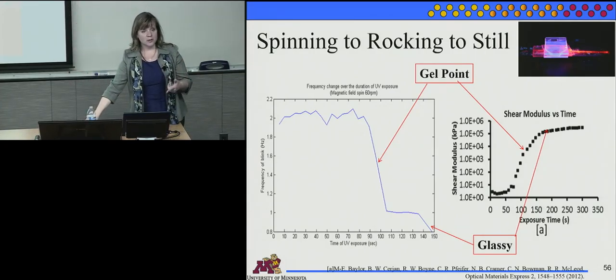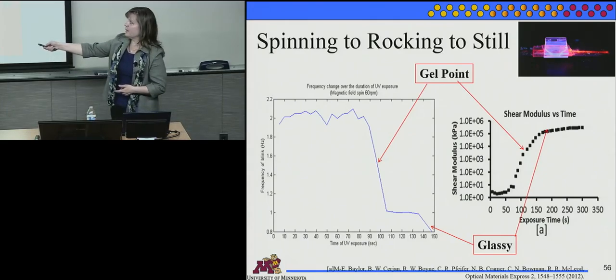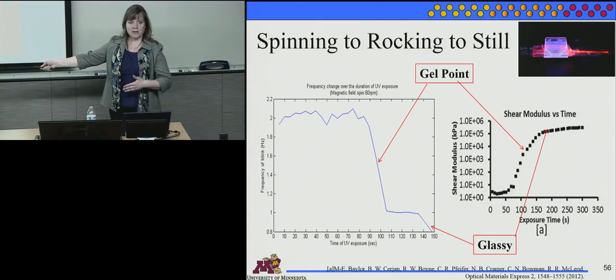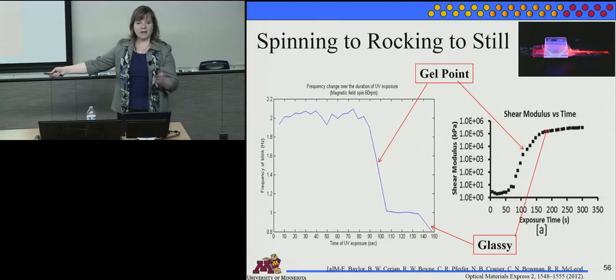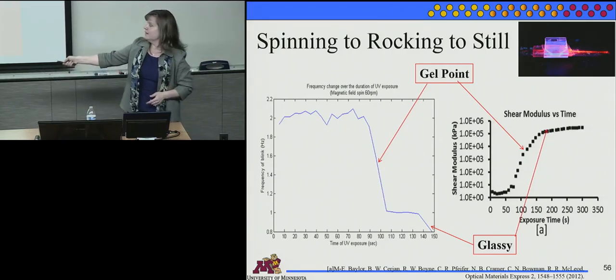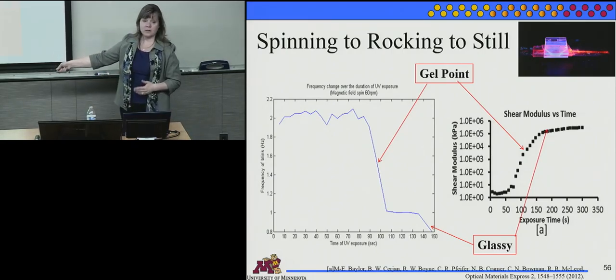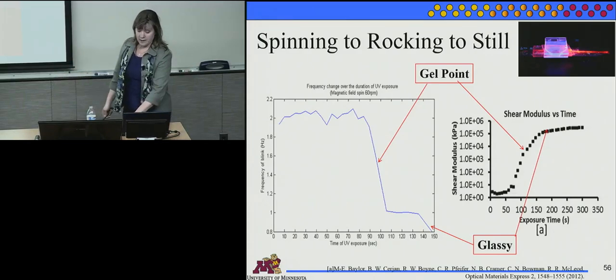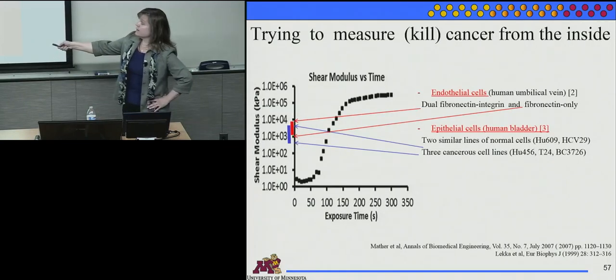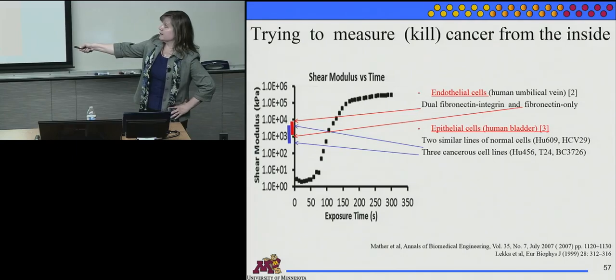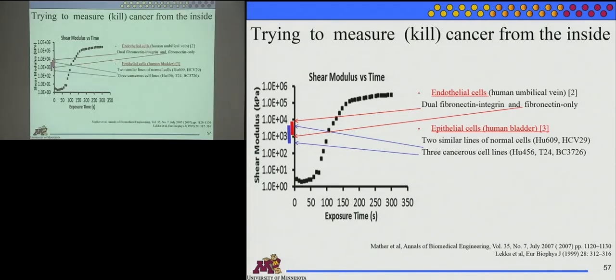As the polymer cures, when you hit the gel point, the wires can't spin anymore. They're kind of stuck in there, and they respond to the magnetic field, but they don't spin. And when you allow it to cure enough that it turns glassy, they don't move at all anymore. And it's convenient that right at that point where they go from spinning, those are the same shear modulus that people measure for cancer cells. And when the wires go to just kind of a rocking, they can't spin anymore, that's the shear modulus that's measured in healthy epithelial cells in the bladder.